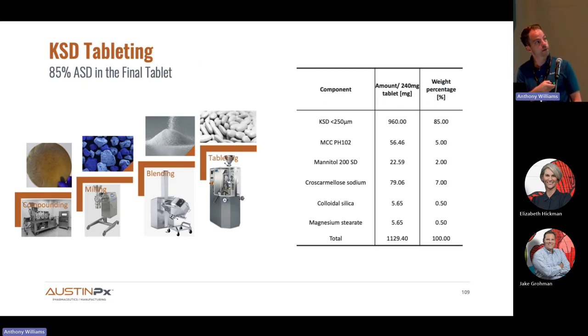I think what's important to point out here is that we were able to arrive at tablets with acceptable tensile strength and disintegration and dissolution performance with 85% of the amorphous dispersion in the final tablet, which will become important later in the presentation. This is key for this product because at the high dose, there's a pretty significant pill burden. The high dose product is very large and difficult to swallow. And for this particular patient population, dysphagia is an issue. So whatever we can do to reduce the pill burden is important. And by maximizing ASD load in the tablet, we're able to significantly reduce tablet size.